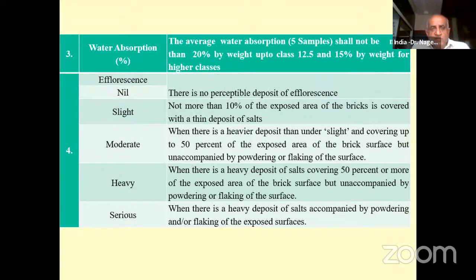Then another important test which you do on clay bricks is the efflorescence test. Efflorescence test is nothing but the presence of salts in the bricks, which will come out when the bricks are immersed in water. We don't completely immerse, only about 20 mm height is immersed. And then after the cycles, when all the water is absorbed, we'll check for efflorescence, whether it's nil, slight, moderate, heavy, and serious. So these are the classifications which need to be verified against the results.